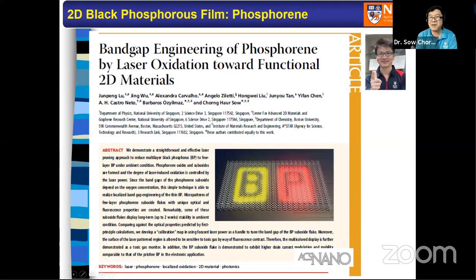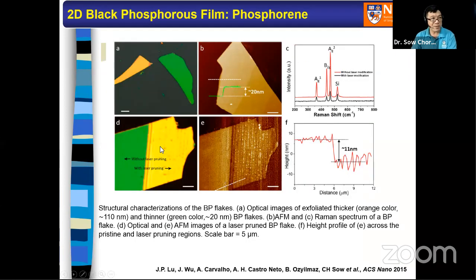This focused laser beam technique can be used for many, many years. So my collaborations with many collaborators always started with, what sample do you have? Give me some, I'm going to do laser modification, and then next thing you tell me, oh, it works. Then we continue on to the next phase of the collaboration. So we take black phosphorus and use laser beam modification. If you play with black phosphorus, you realize that these materials get oxidized very easily, so they become not so useful and degrade fast. So we use the laser beam to intentionally oxidize the surface, to have a certain degree of control of the phosphorus oxidation state.